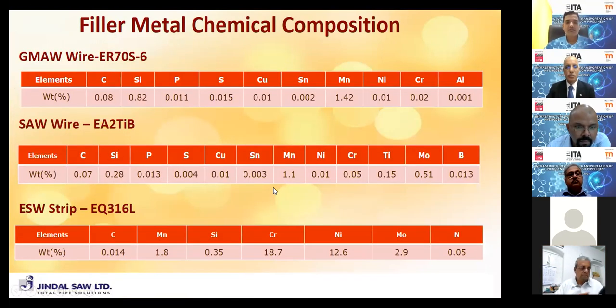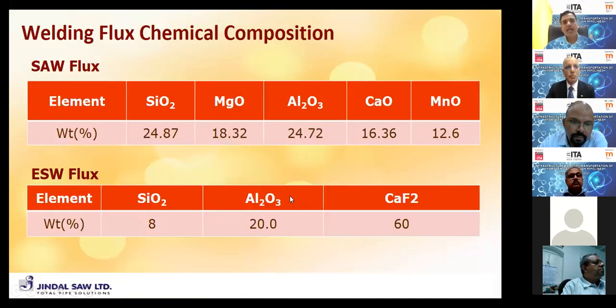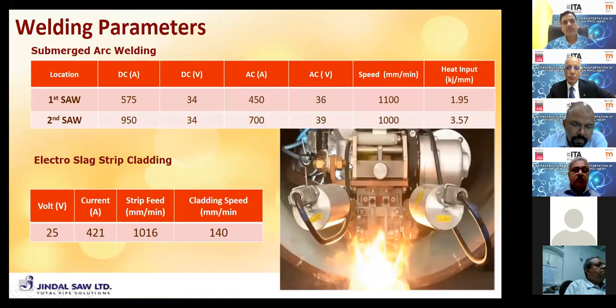Next slide, please. So we have used normal carbon steel consumables, which are widely used in pipe mills, like ER70S-6, and titanium boron wire, and the strip that is 316L. Next slide, please. The chemical composition of the flux: for sub-arc welding we have used aluminate basic flux, but for the electroslag welding, CaF2, calcium fluoride basic flux is used. Next.